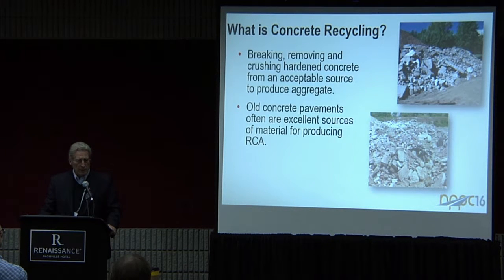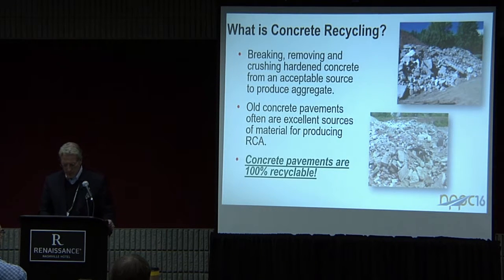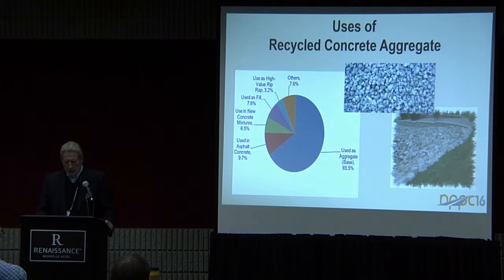But typically for highway paving, we've got pretty stringent requirements, at least on recycling back into mixtures of various sorts. We tend to be sticking to things that we know the quality of, we know the background and the history of, and that would be the concrete pavement materials there. They are 100% recyclable, concrete pavements, just as the asphalt pavements are. I think people overlook that a lot of times. Even the fines are recyclable. We're finding a lot of uses for the fine materials now that didn't used to be out there in the past. Those uses for both fine and coarse material include the things that you see here.